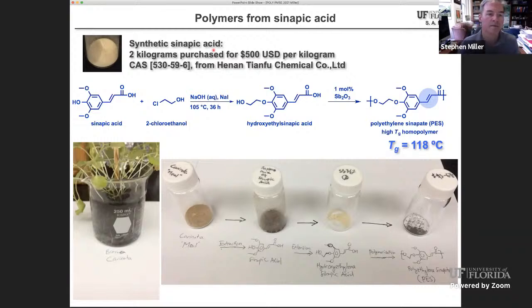Typically in large scale production, several gram production, we will use commercial, that is synthetic sinapic acid, which you can buy, I think, from alibaba.com. We probably dropped $1,000 on this, which is fine. So it's not the cheapest thing out there, but it tends to make a polymer, this polyethylene sinapate, with a Tg of about 118 degrees, which is good for us.